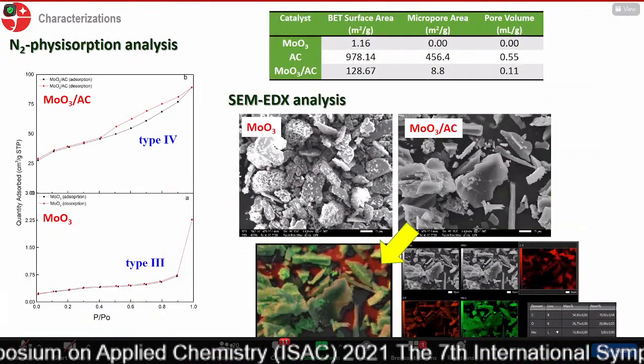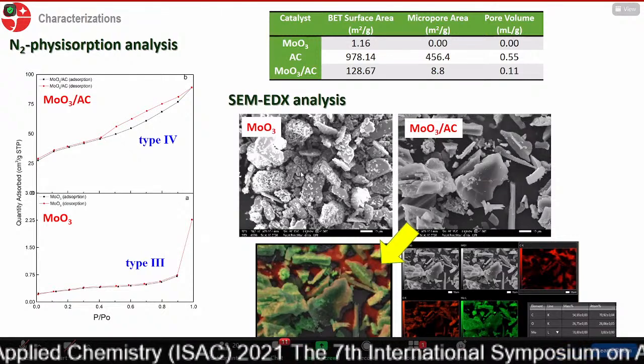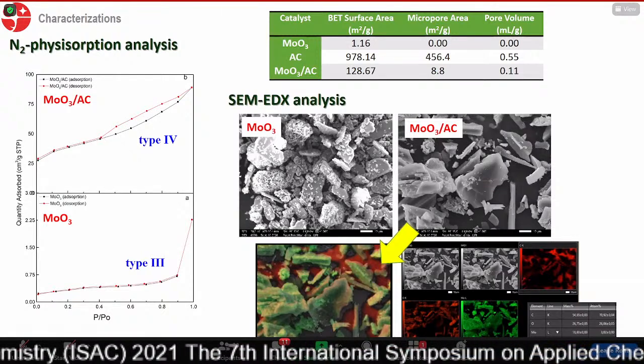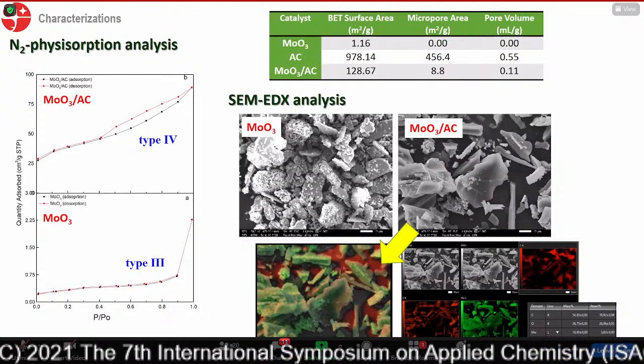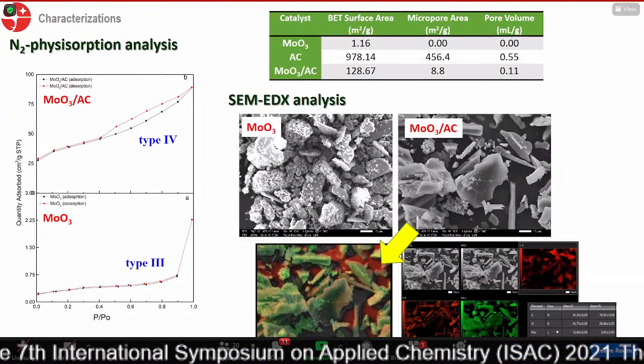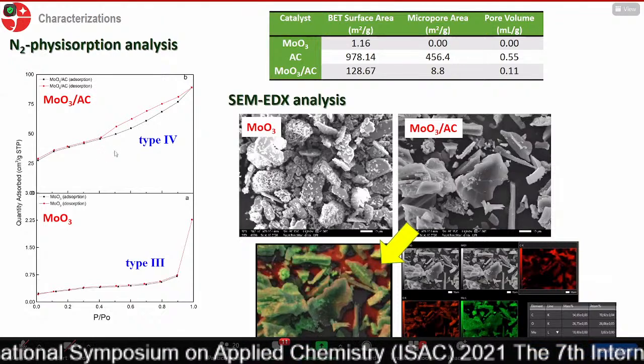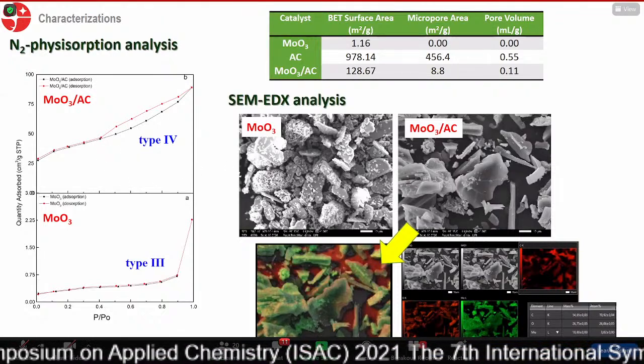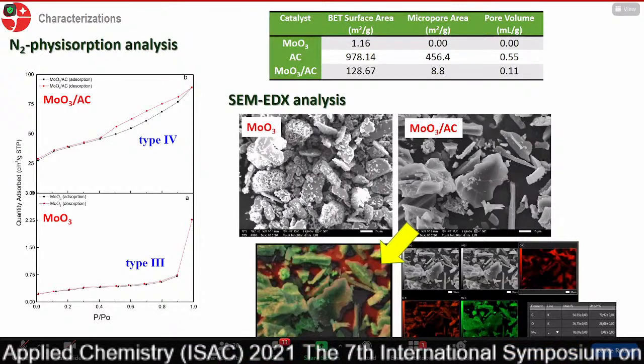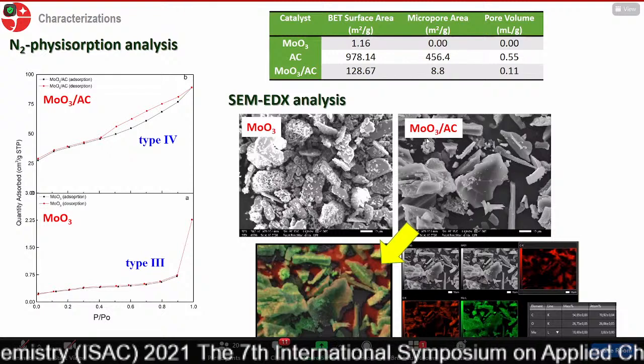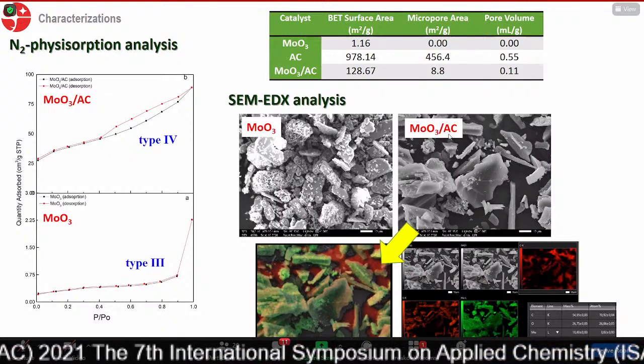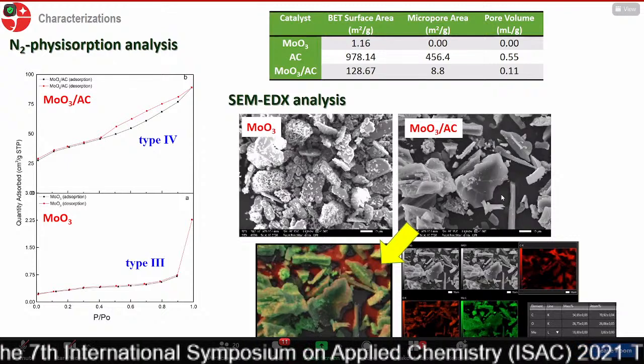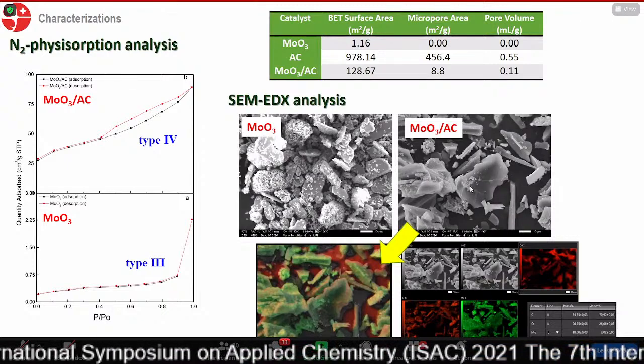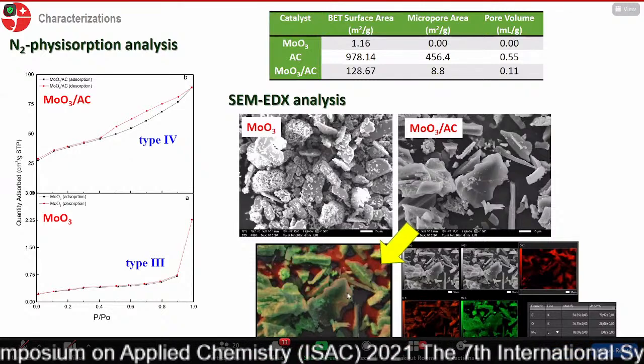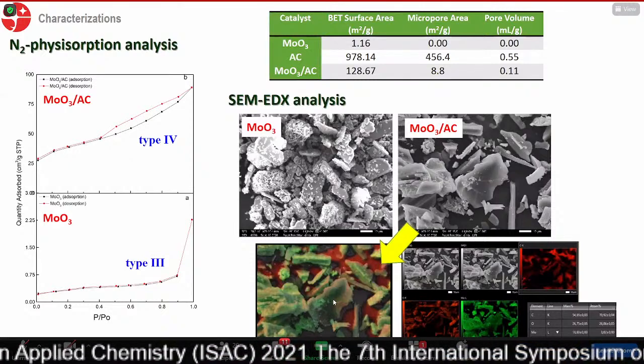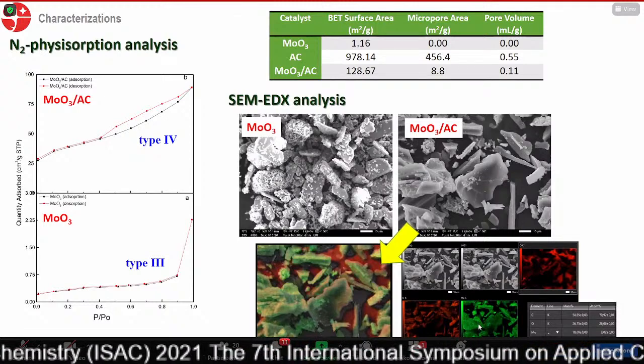As you can see here, this left part is our bulk molybdenum oxide, which we obtained from the calcination of ammonium heptamolybdate directly. And this is a very big particle size of molybdenum oxide. Then we compare it to our molybdenum on activated carbon. This is the size of the activated carbon that we have, and the molybdenum is this tiny green dot.